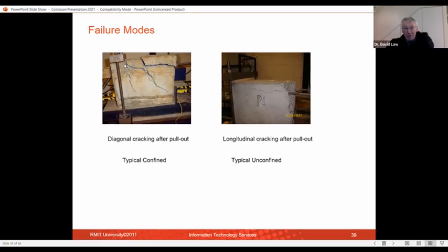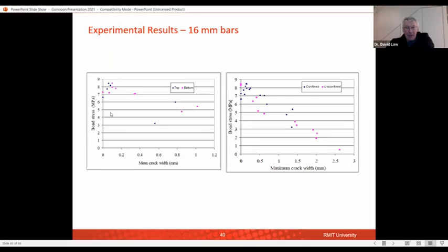Here, sort of typically after cracking, after bond failure, we get these cracks, and sort of here we have another one where it comes straight out, where we've just got the longitudinal cracking. This was typical for unconfined. This was typical for confined, as you might expect. And these are the sorts of graphs that we got.